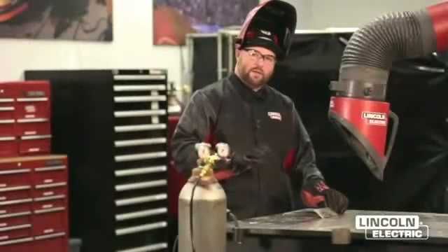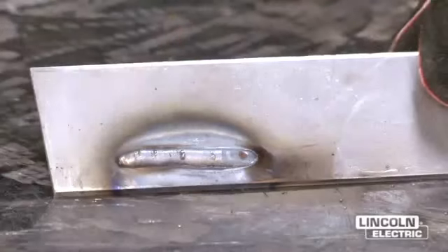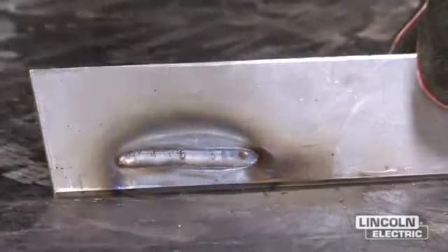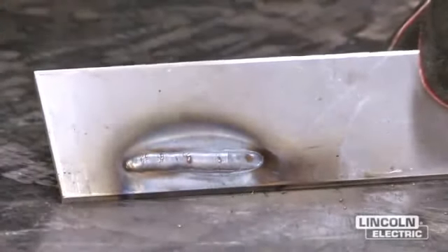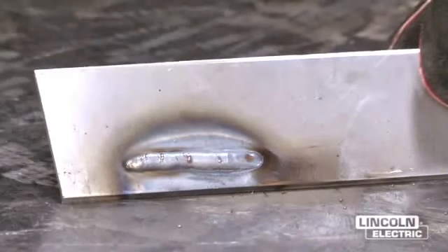So if you notice by looking at the arc, we can see that the weld puddle is really piled up and our travel speed for this particular material was too slow.